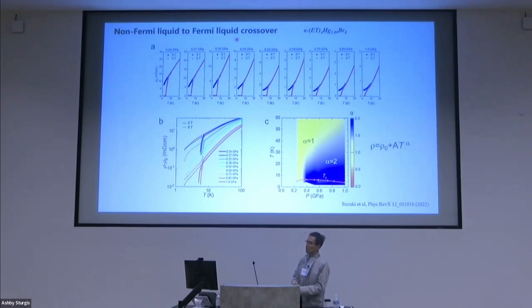With a magnetic field you completely suppress the superconductivity and you don't impact that point. Would you expect to see the T-linear resistivity? If you suppress the superconductivity, you still expect T-linear resistivity down to... In these experiments, 1.5 kelvin is the lowest temperature studied. Am I asking about higher temperatures? Okay, higher temperatures.